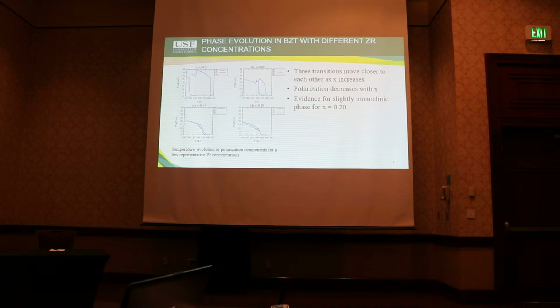At 8%, we have the 3 phases that move closer to each other. And we can see that not only do the phases move closer to each other, but the general polarization of the cell is reduced. This is expected and does match well with the experimental findings.